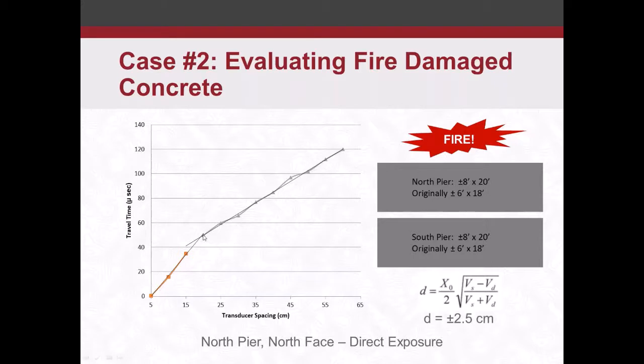Probably could have included this point here. With this data set, it wouldn't have made much of a difference. But certainly over here we can see the slope of these points is different from the slope of these points here. So we know we've got varying wave speeds. So when we apply this formula here, we get the depth of the fire damaged concrete was about 2.5 centimeters.